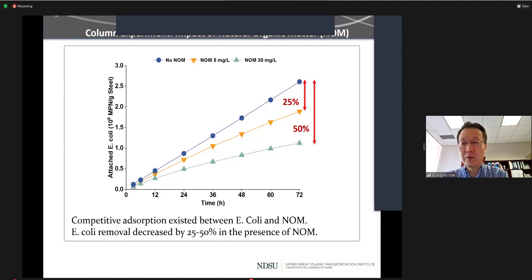So the blue circles indicate there is no natural organic matter. Then we added 5 milligrams per liter of organics into the influent, as indicated by the yellow triangles. And we also increased the organic matter concentration to 30 milligrams per liter, as indicated by the green triangles. And we found that as we increase the concentration of organics, the E. coli adsorption efficiency declined. And the percent decline is 25% for 5 milligrams per liter and 50% for 30 milligrams per liter. So if the stormwater has high concentrations of organics, it may reduce the E. coli removal efficiency.